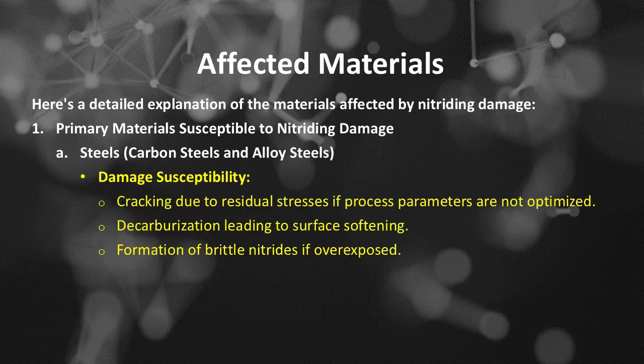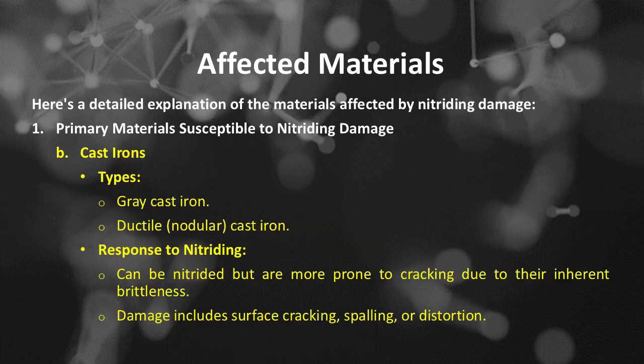Damage susceptibility includes cracking due to residual stresses if process parameters are not optimized, decarburization leading to surface softening, and formation of brittle nitrides if overexposed. The next primary material susceptible to nitriding damage is cast irons. Types of cast iron include gray cast iron and ductile or nodular cast iron. Their response to nitriding can be nitrided, but they are more prone to cracking due to their inherent brittleness. Damage includes surface cracking, spalling, or distortion.